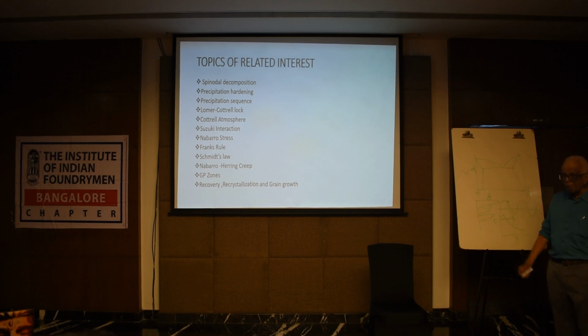Into GP zones or whatever. Guinier-Preston zones are the first stage in the precipitation sequence. For example, in an aluminum copper alloy, when you solutionize it, quench it, and age it, first the formation is by Guinier-Preston zones. Guinier was the French scientist who discovered it long back, and then Preston in England also saw the same thing by X-ray diffraction. So that's GP zones, metastable precipitates and equilibrium precipitates.